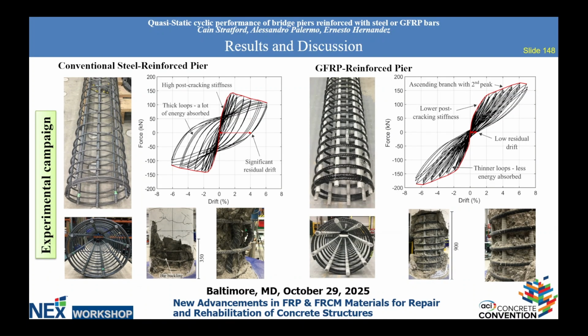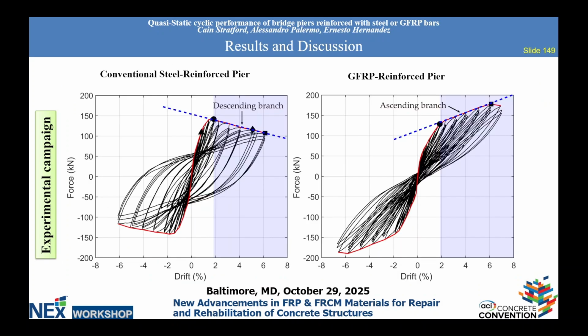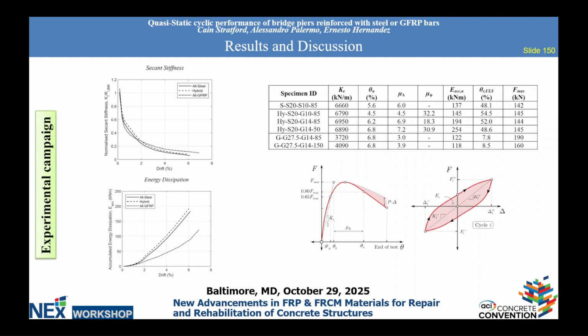So I'm not saying this is the solution, because you say, oh, we need to dissipate the energy. But what I'm just showing is that there were surprises. I mean, it was actually good, yes. What I want to show you is that having an ascending branch is quite positive in a way, because if we put those two specimens on the shake table, I can guarantee that the displacement demand will not be 3 times more, even though we have 30% of the energy dissipation. That post-yielding and recentering is probably giving 20-30% more displacement demand. So this is quite positive. So ductility is important, but we have to think that there are other parameters. The recentering is also very important. So this is pretty much the summary.